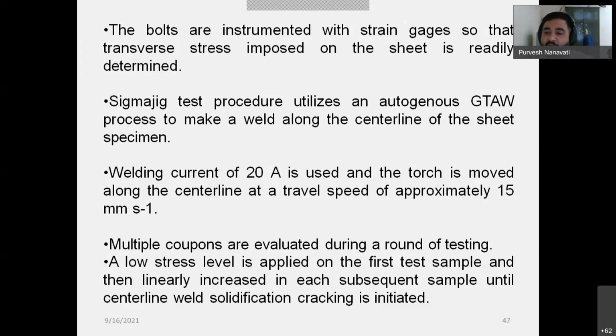So you first start with the test sample. You start with the low stress level, then you start increasing your stress level, and you go on increasing until your centerline weld solidification crack is initiated. It means you start with say 3%, 4%, 5%. Say at 7% or say at 11% your crack is appearing, then this is your stress level, right?